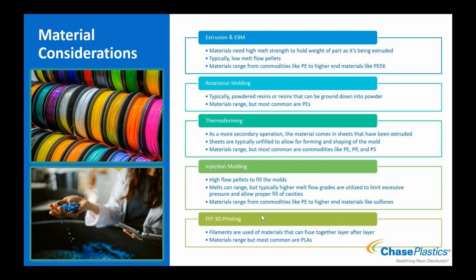Then injection molding, like extrusion, has a huge range, anywhere from your commodities all the way up to your high-end materials, sulfones, PEIs, run the gamut. It just depends on what you're making and what you need the material to be doing. That will dictate what material we're going to use. But in these cases, we typically use a higher melt flow material. We want a little bit less of the chain entanglement. We want it to flow a little easier, and we don't want to have to utilize a ton of extra high pressure to get the material to flow.